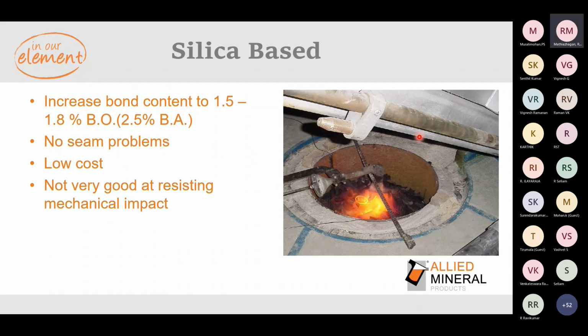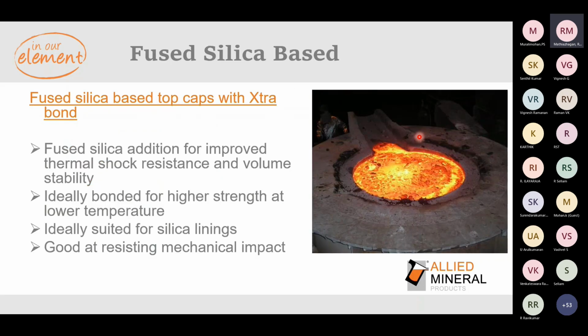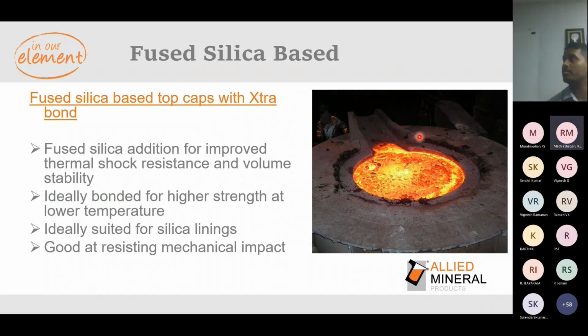So when we are talking about top cap refractories, it can be either dry, wet, or plastics. For silica, we engage all the above said, like plastics or castables or dry versions. This is one type, silica based, where we increase the bond percentage. For example, if you're using 0.8 or 1% boron oxide for the main working lining, the top caps can be done with 1.5% B2O3 or 1.8% B2O3, so that this product sinters a little bit at low temperature and gets the strength. This is one of fused silica based top cap materials with extra bond. We normally recommend fused silica based materials on the top to have good volume stability.